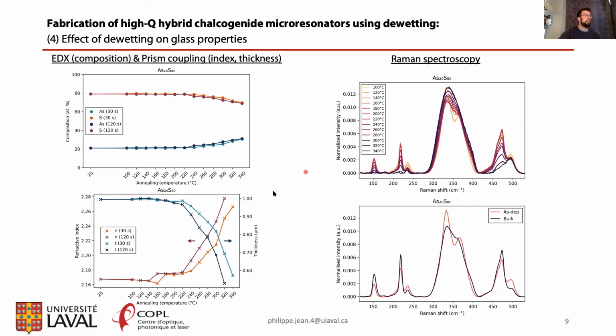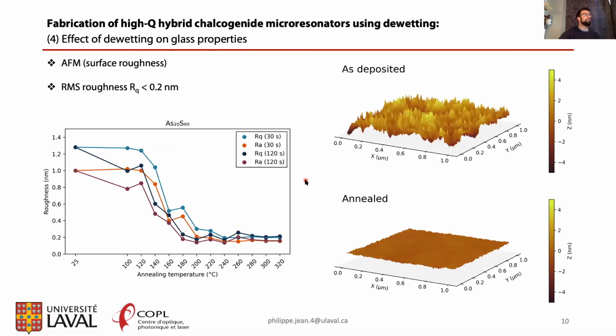And what is really important to notice about these is that there is really a trade-off between achieving aggressive dewetting while preventing evaporation of the material, or having actual compositional change, so losing the stoichiometry of the material. And also what is interesting to notice is that according to the Raman curves, it's possible, using a very fast annealing that induces dewetting, to actually go back to the bulk state of the glass. So that's important for thin films that usually don't have properties that are very close to the bulk state.